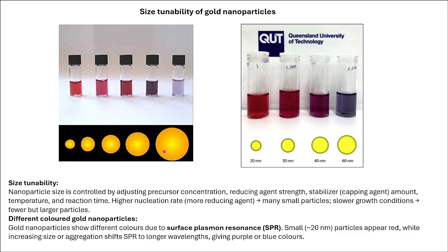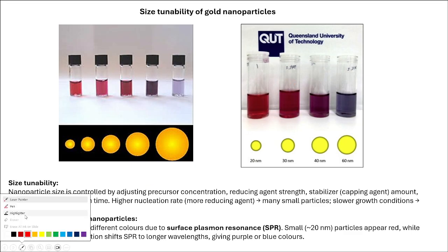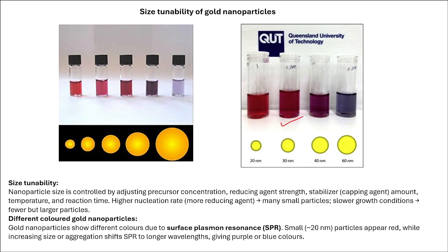But before that, as a preliminary means, if you look at this image, even before you have done electron microscopy to see the image of nanoparticles, even if you have not checked its zeta potential value, its size and everything, its absorption spectra, just by looking at the color, if you're getting this red wine color, you can say that the particles could be somewhere in the range of 20 to 30 or 35 nanometers.